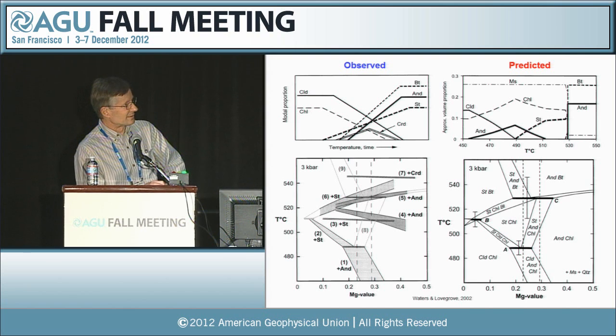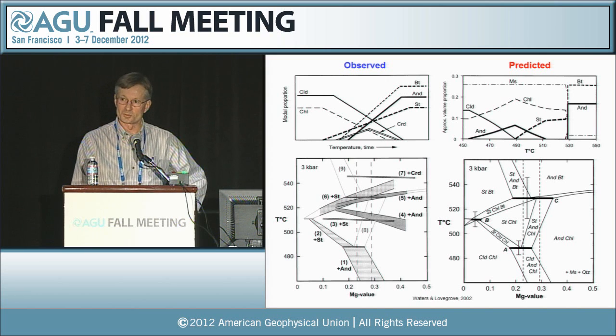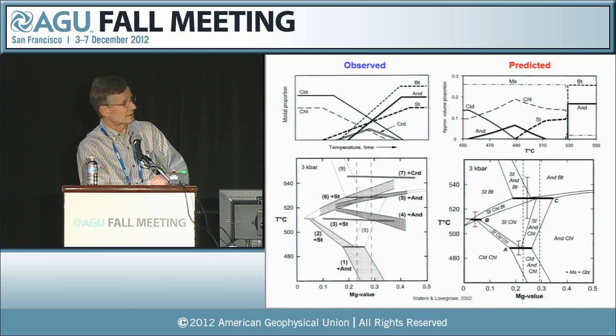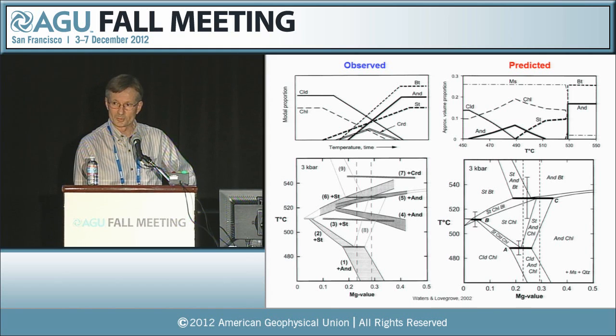So the next step they did was to take the bulk composition of the rock and calculate an equilibrium phase diagram, which is shown in the lower right. This is an isobaric TX diagram here. And for the bulk composition of interest, which is between the dashed lines, they could predict what the modal changes would be going up grade. And the result of that was this mode versus temperature diagram.